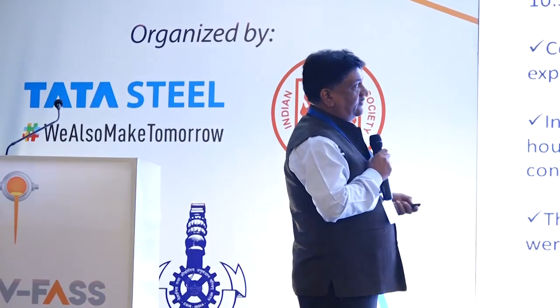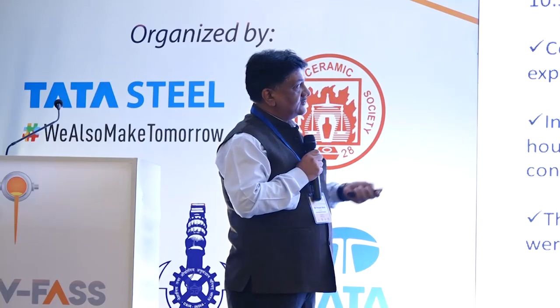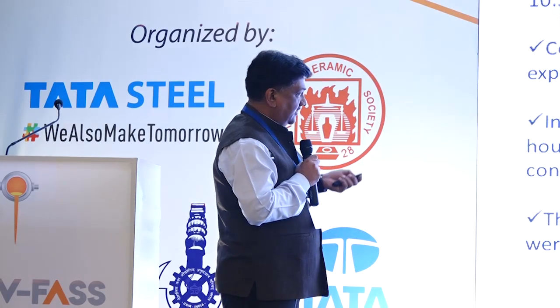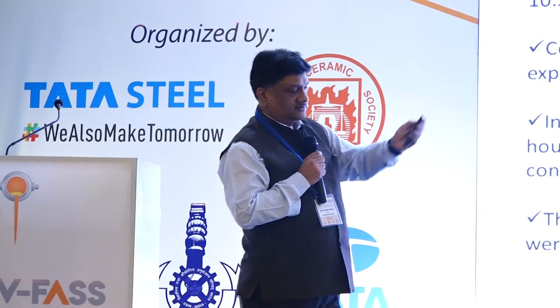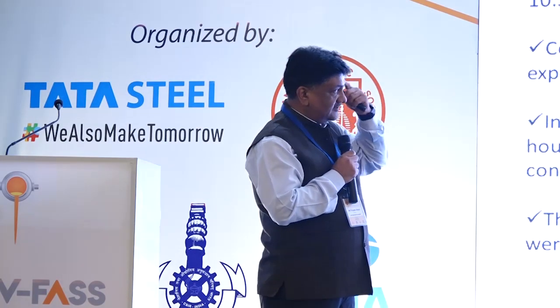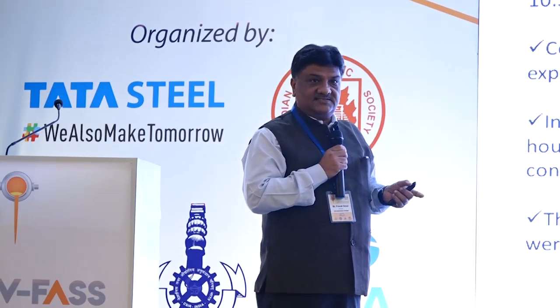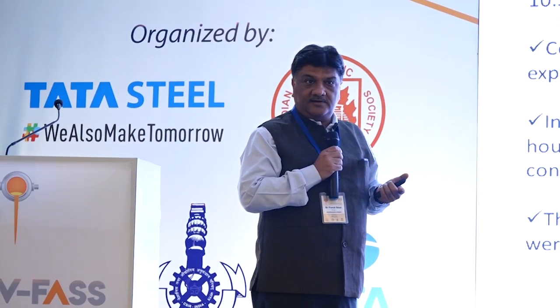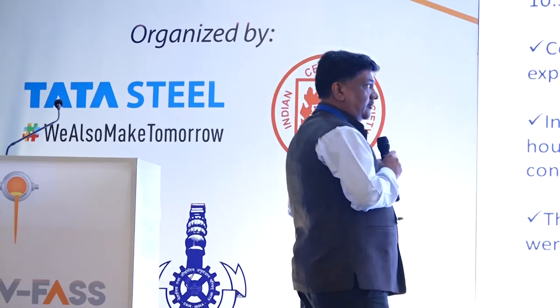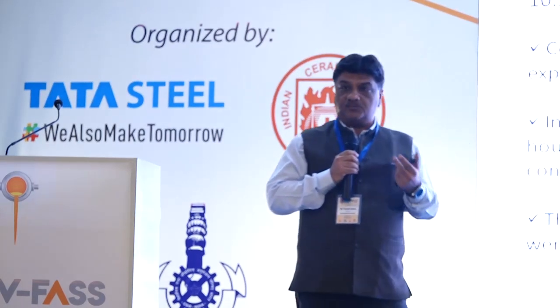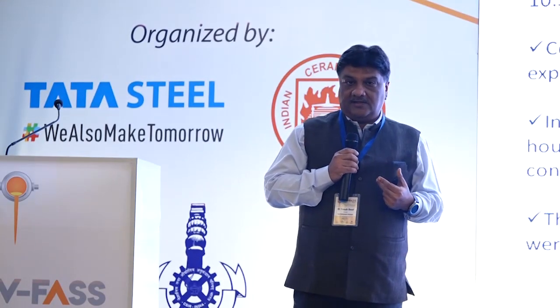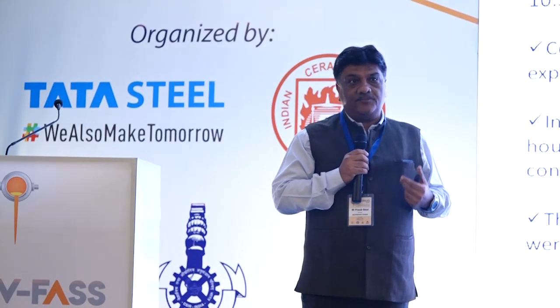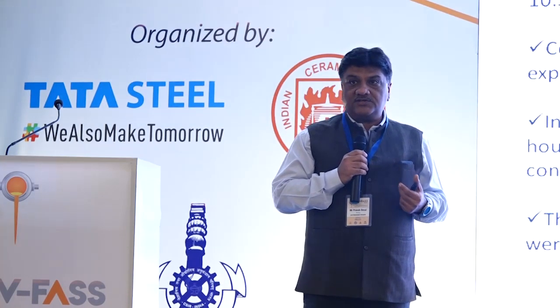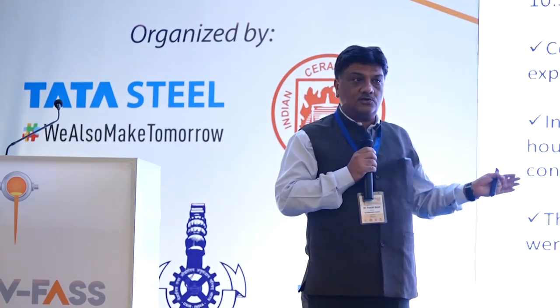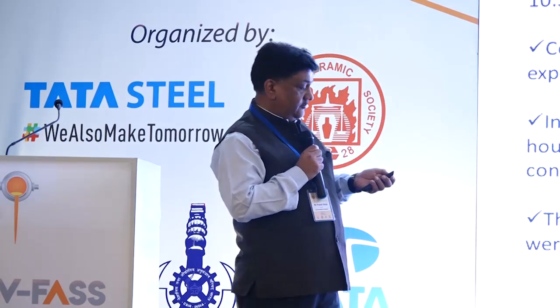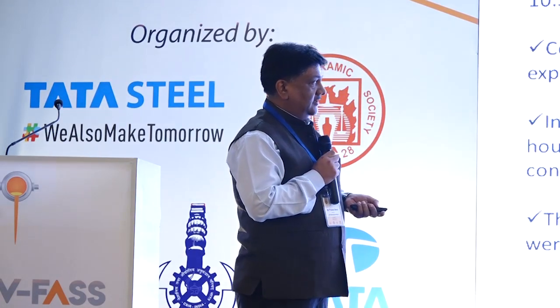The fly ash was sourced from Reliance at Hajira in Surat, where the LOI was found 10.53%. And we used that. You can compare both. The pointer is not working, but you can see the properties. There is a little bit higher demand on the plasticizer because it has an unburned carbon. But what happens if you are not using such carbon blocker, then it will absorb more water. If it absorbs more water, it will demand more cement, and it will become uneconomical. So that is the main blocker for the user while using the pond ash or coarse ash or other unburned carbon ash which are lying in the dikes.